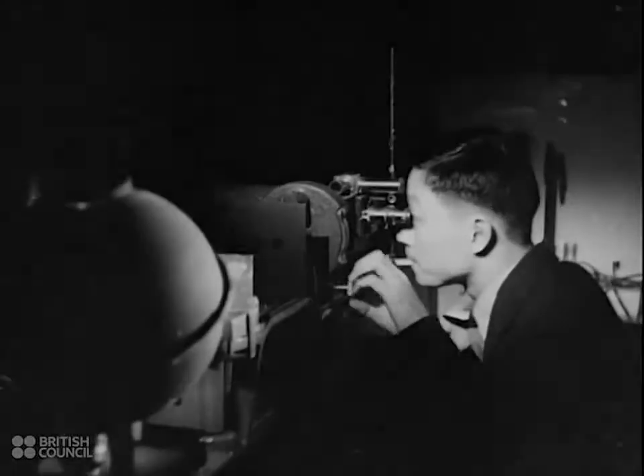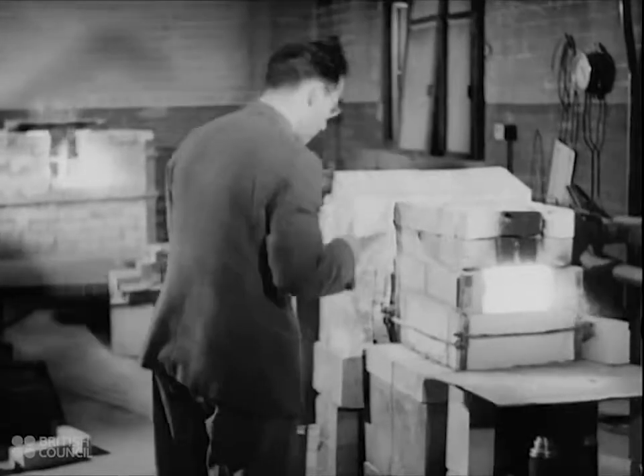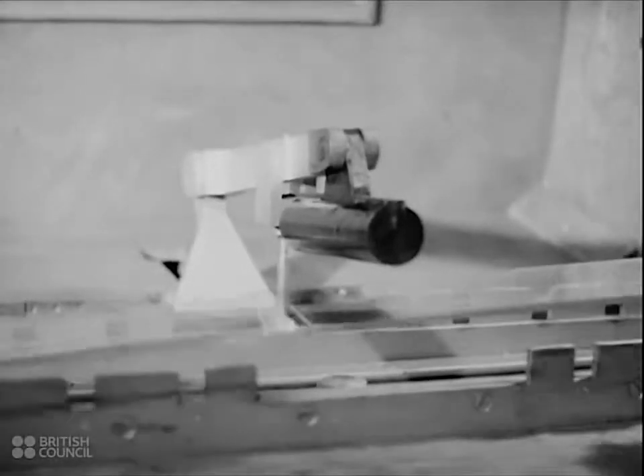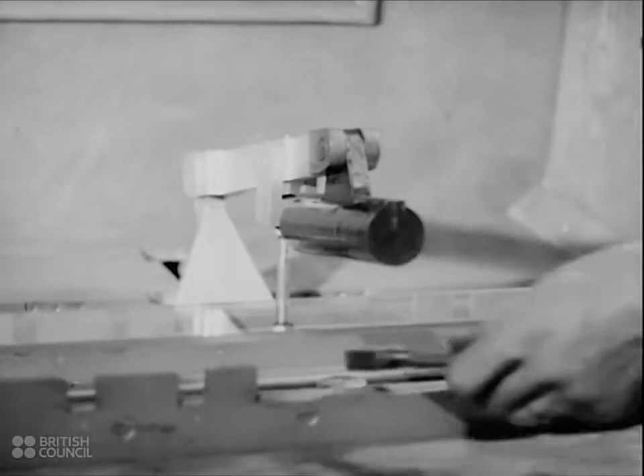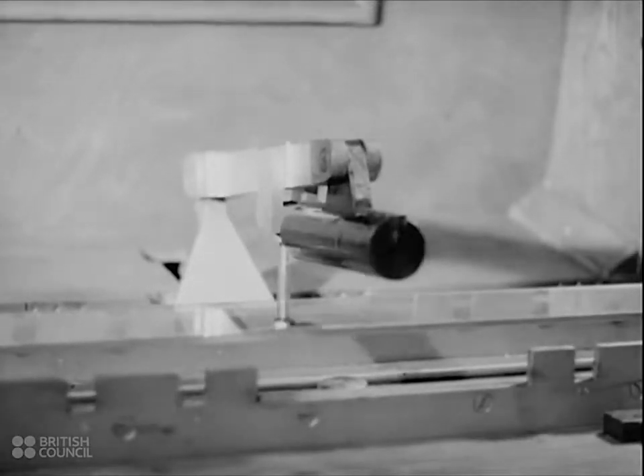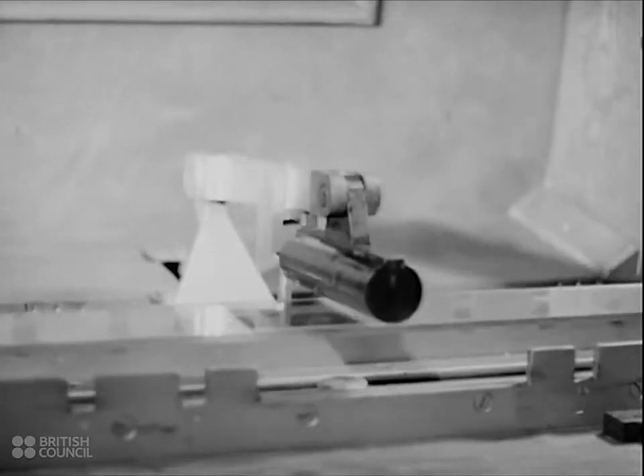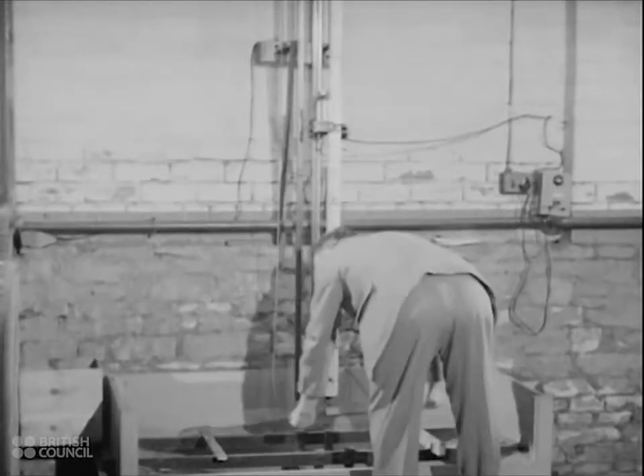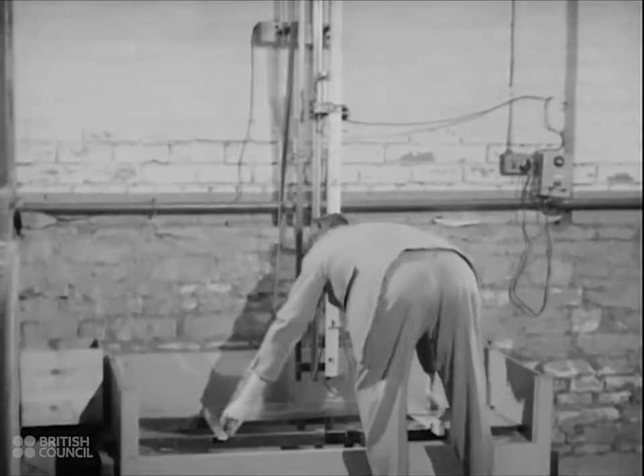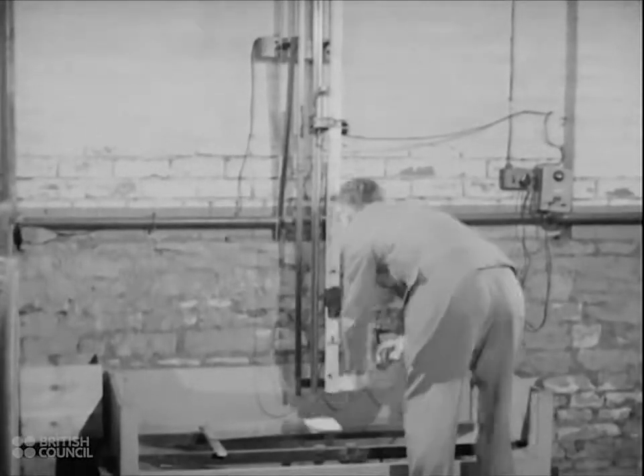In these well-equipped laboratories, the problems of glass are studied scientifically, and the results quickly conveyed to manufacturers through visits of Professor Turner and his staff, and through the Society of Glass Technology, a pioneer body with membership throughout the world. Here, a specially heat-treated safety glass windscreen is being tested. First, a bending test for pliability. Then the safety glass is tested for resistance to smashing by dropping a metal ball on it from a height of 8 feet.